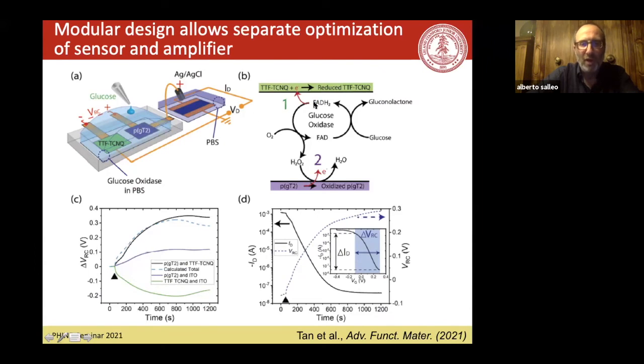But on the other side, the cofactor that got reduced can itself get oxidized and reduce the other electrode. So it donates an electron here. So this becomes more positive. This becomes more negative. So I get twice the bang for my buck. My glucose molecule, if I only use the reducing electrode, I get a certain change of potential, about 200 millivolts. If I only use the oxidizing electrode, I get about 100 millivolts. If I use the two together, I get the sum.